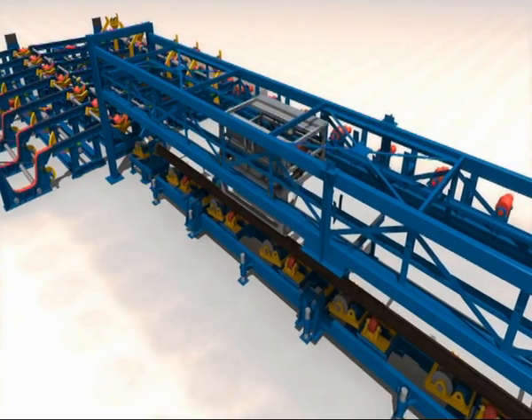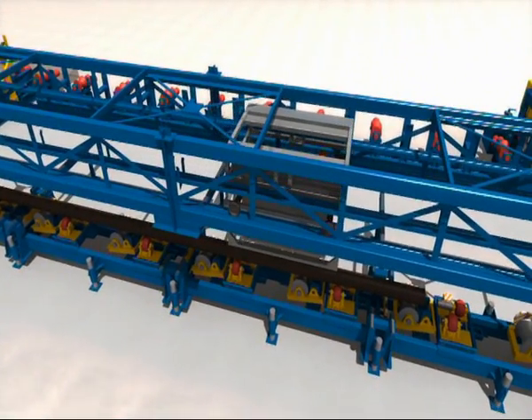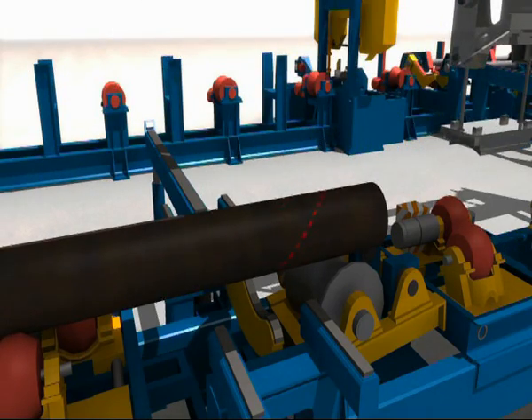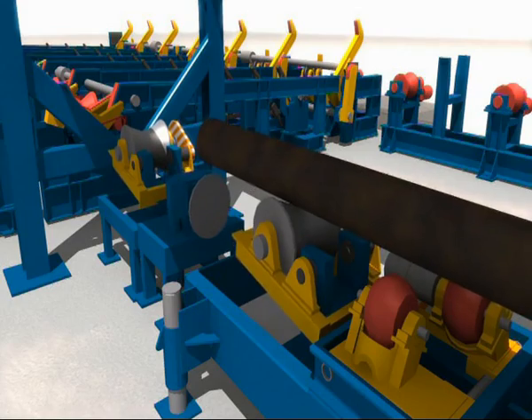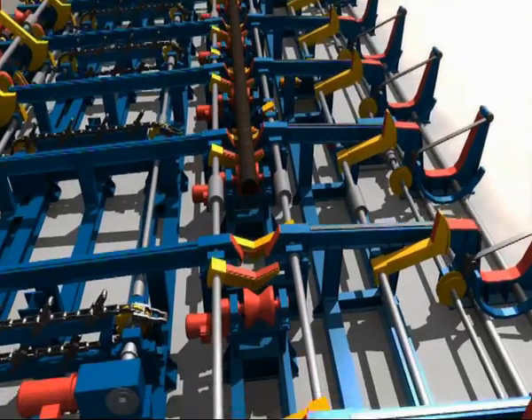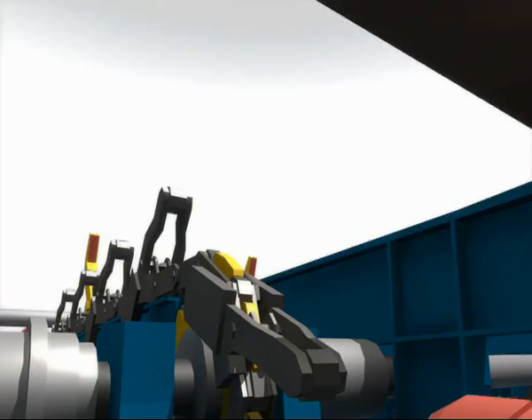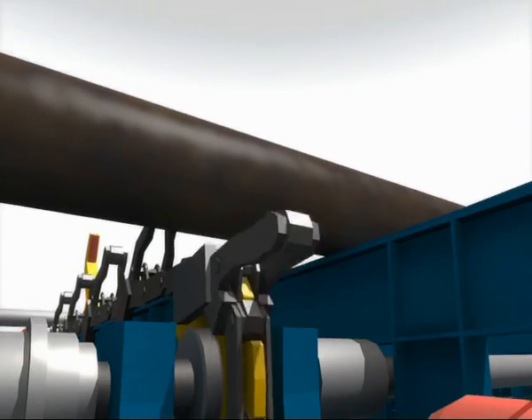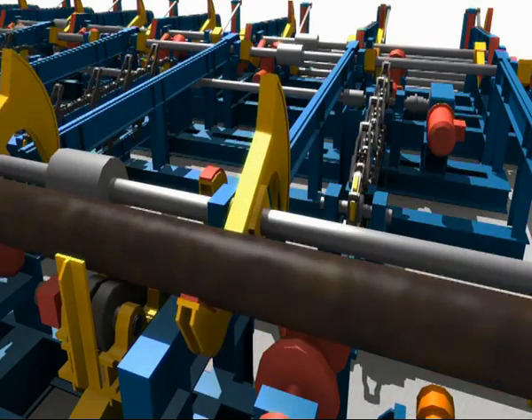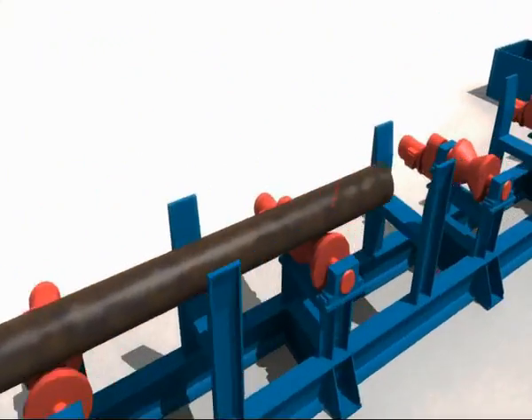The double level of the inspections performed, EMI, electromagnetic inspection on the line of quality assurance, and UT, that is ultrasonic testing on this line, is the best way to guarantee the production of pipes without defects. The capability of the line ranges from 2 3/8 inches to 13 5/8 inches. It has a nominal production capacity of 90,000 tons a year, and it can process every type of product as long as it is straight enough and the ends are without fins or residual cuttings.